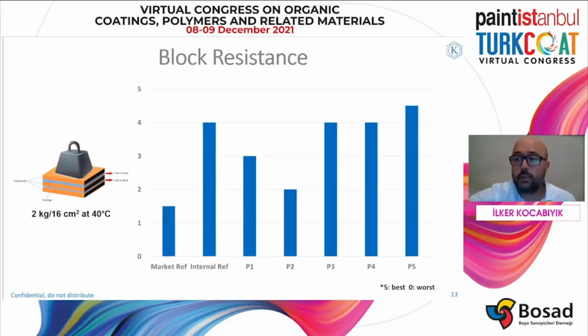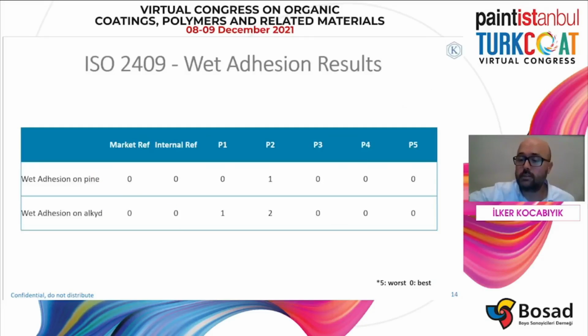Blocking resistance of the paints was tested with an internal method. The paints are applied to 100 micron on black PVC panels. After drying, films are stacked with 1.25 tons per square meter at 40 degrees Celsius. Blocking resistance is assessed according to a 0 to 5 scale, where 0 means completely blocked paint films and 5 means there is no blocking. Lowest hot blocking resistance was obtained with the market reference polymer. Internal reference P3, P4, and P5 showed better hot blocking resistance.